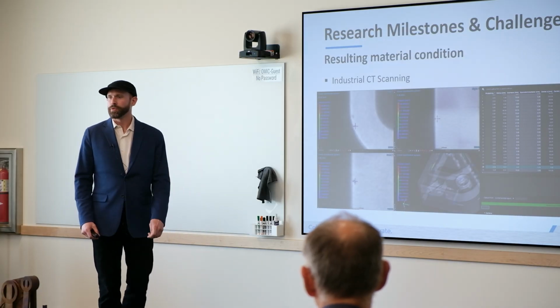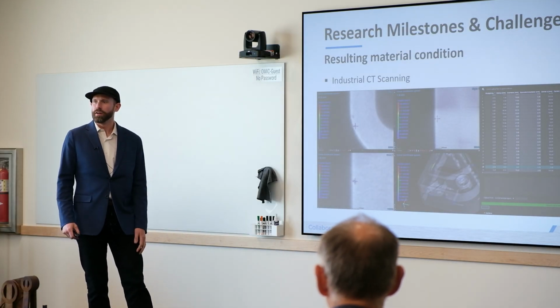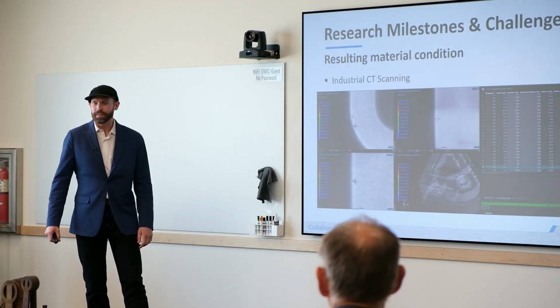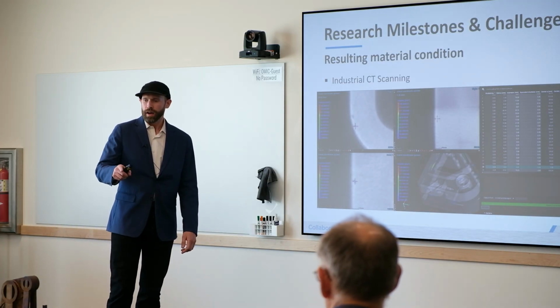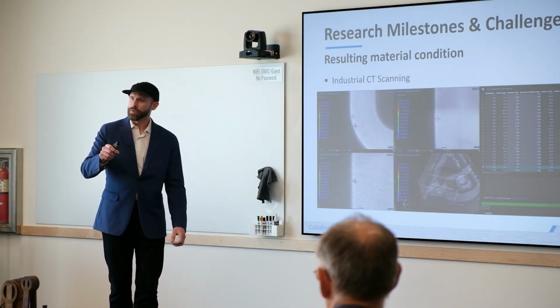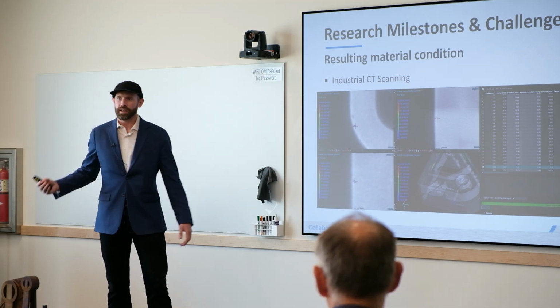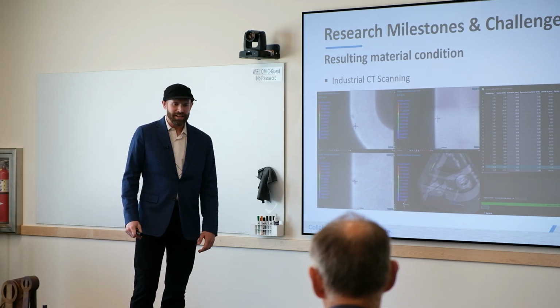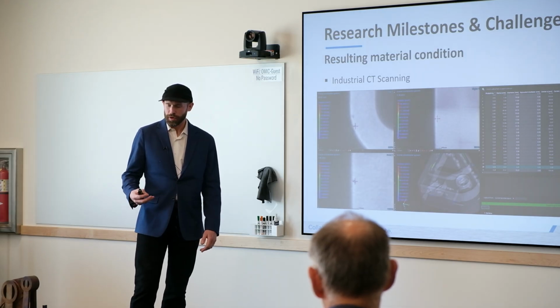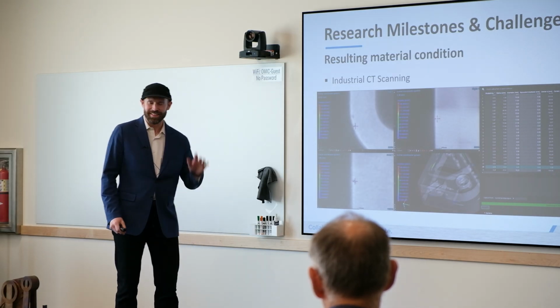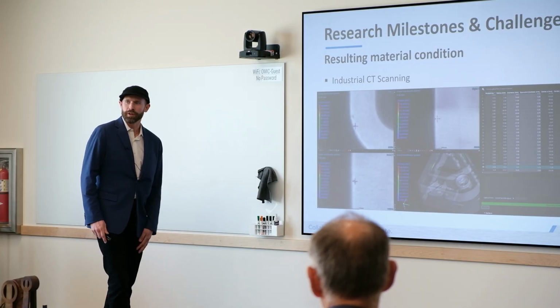They're large. So we were able to squeeze a large amount of inconsistencies out of these parts, and you can tell that in machining. With the non-hipped parts, you were cutting through, opening up voids, seeing carbon layers, and just getting a general abrasiveness to your cutting tool that we did not see after hip treatment of these parts.